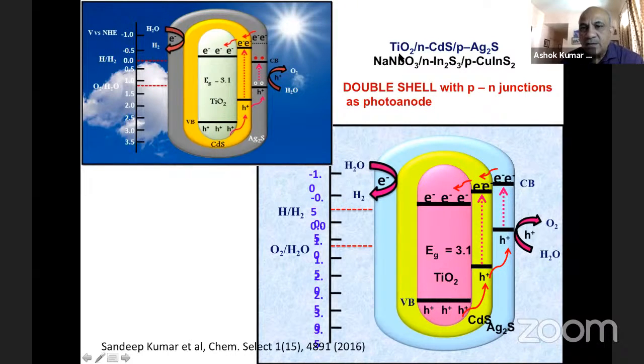So you have a TiO2 core, which is the UV catalyst, and we have an N-type chalcogenide semiconductor, cadmium sulfide. On top, you have a P-type semiconductor. So what we have done is you have a UV photocatalyst, then on top an N-type semiconductor, and then a P-type semiconductor. This design was extended to another set of materials. The property is the same. This is a UV catalyst, sodium niobate. You have an N-type semiconductor and you have a P-type semiconductor.